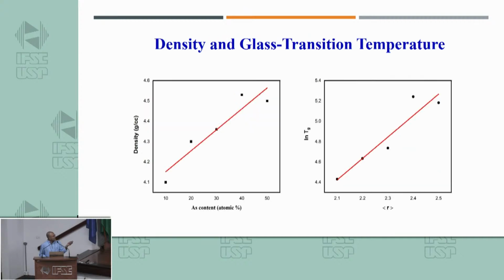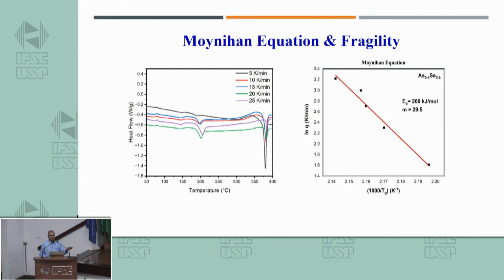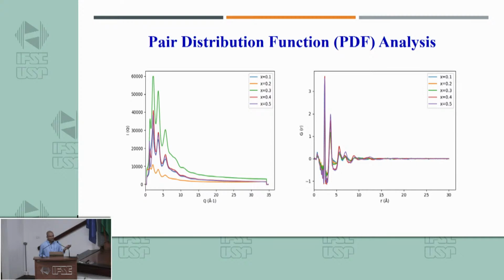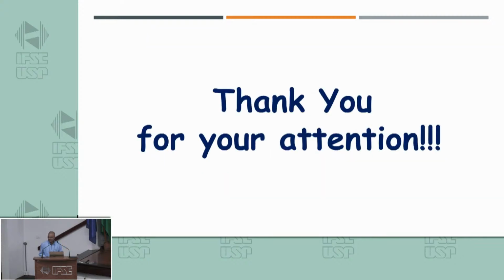And then we know that this glass transition temperature also has a relation with the viscosity, or we say fragility. So in order to get an idea of how fragile my glass is, we have done differential scanning calorimetry at different heating rates, and then tried to find out the fragility index for that. And lastly, in order to get an idea of the structure, I have tried to do pair distribution function analysis, so that I can know how the changing composition is changing the structure, which in turn is determining the properties of my glass. So all this I will try to discuss in my poster. Thank you for your attention.